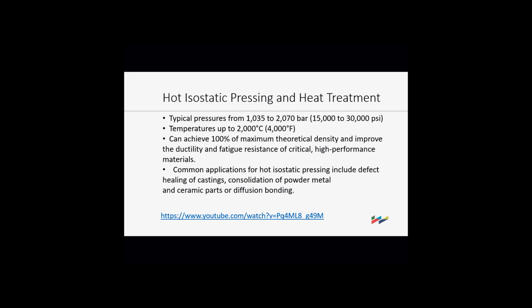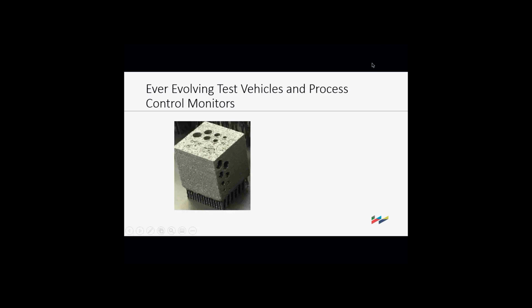you're going to end up with a lot of shrinkage. One of our goals when we designed the process was to try to avoid doing hipping, because it could be two weeks turnaround time that we have to wait for the product to come back from the HIP process. So we strive very hard to get the porosity down to a very small percentage. With HIP, you can hit 100%, and I know that's for a fact because I've done it.